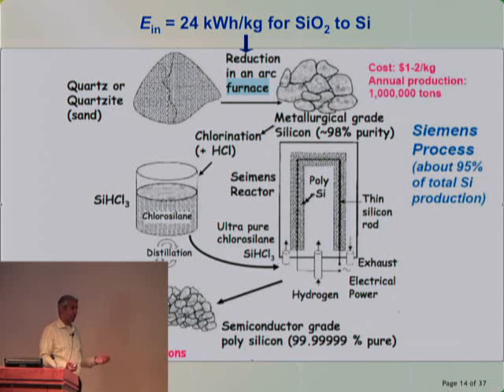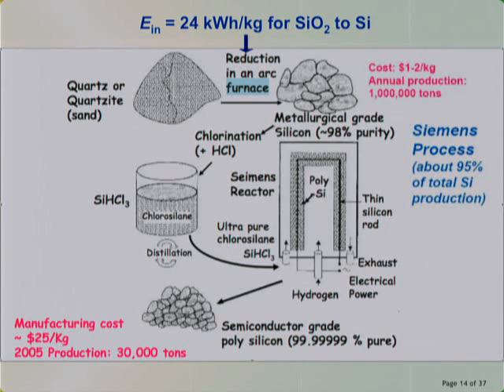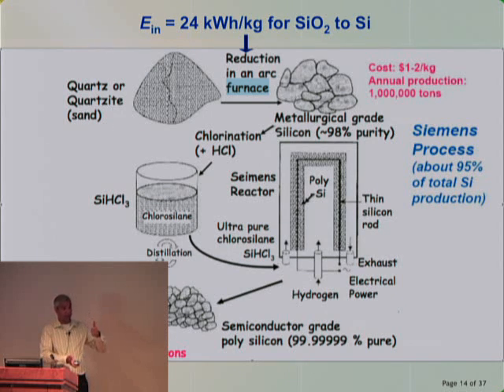Now, the question you might ask is, why so pure? Well, with silicon, this is all determined by the physics of the material. Silicon has what we would call a very poor absorption property, or absorption coefficient, meaning we need a very thick material relative to other semiconductors to absorb the same amount of energy. When you make it thicker, what you're adding is a longer pathway for your electrons to move out of the device. And when you do that, you have to ensure that you have a very pure bulk material. Otherwise, your electrons will get lost. So as you grow a film in this direction of thickness, you have to increase the purity to compensate for that. This is one of the hurdles for silicon.